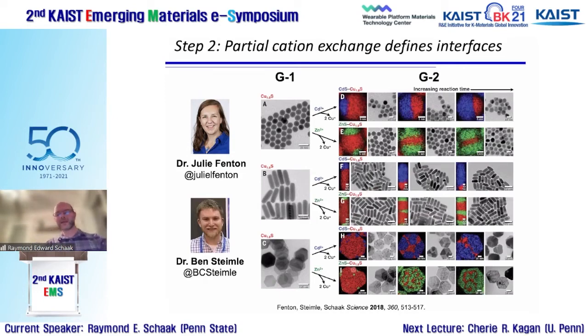I'm not going to talk about the plates, but there's a variety of patchy and marbled structures that emerge. But the key thing I want to point out is that this second generation stage is where we've done the first partial cation exchange reaction. The key thing is it's defining interfaces. And you can probably guess that there are different interfaces because of the different ways in which these reactions progress. So defining these interfaces, we can then take these second generation structures that have interfaces defined but still some remaining copper sulfide. Copper sulfide is the component that's easily exchangeable.